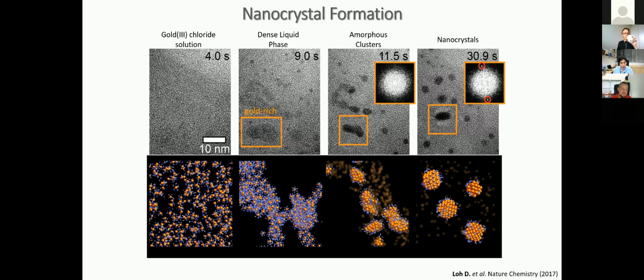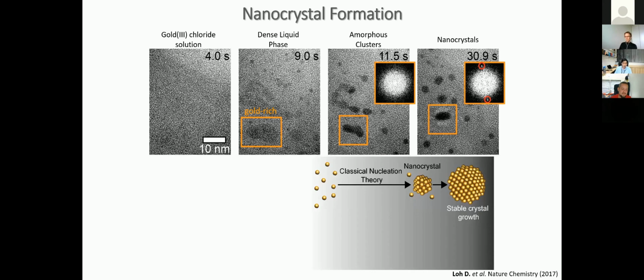So you can take a Fourier transform of many of these particles, and I think we've looked at 15,000 of them, and it is not crystal; they're all amorphous. And at a certain phase, at a certain time point, this thing crystallizes. So you start with a solution that phase separates into dense and poor, gold-dense and gold-poor regions, and the gold-dense region just collapses into a particle, which then crystallizes. Schematically illustrated here.